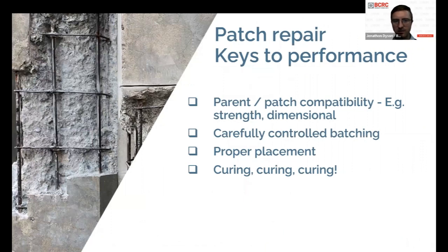Also, there are many other things you need to consider for a good patch repair, such as the compatibility of strength, dimensional shrinkage, etc., thermal movements between the patch repair material and the parent concrete. What we've seen a number of times on sites is very, very poor control of the batching of the patch repair material, particularly if you're using a bagged cementitious product. So that's really important, that the batching of the material is done consistently and in a controlled way. We've seen so many examples of too much water being added or too little water being added, and it really does affect the outcome of your patch repair.